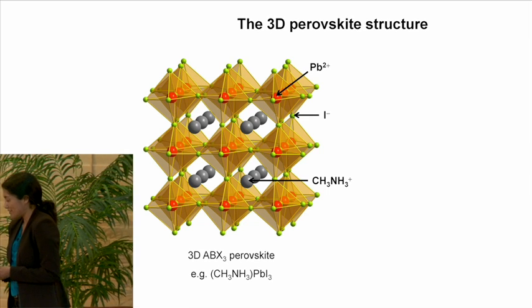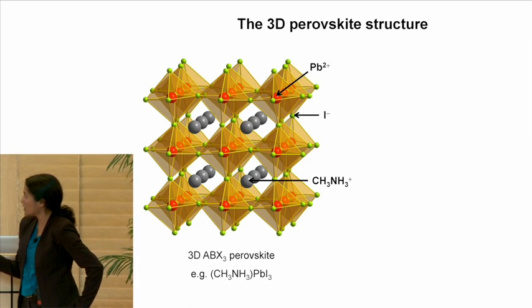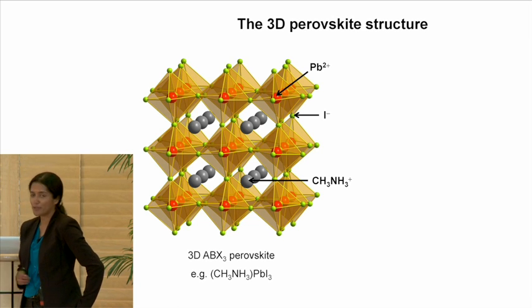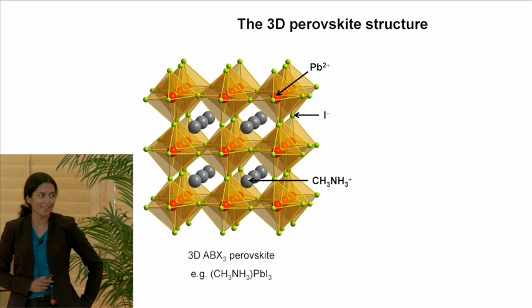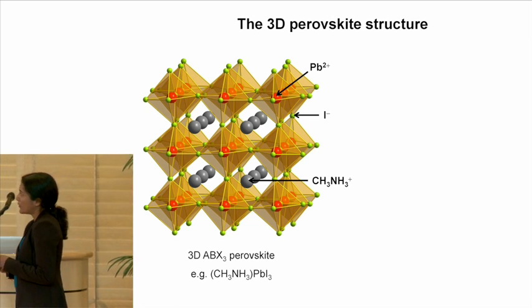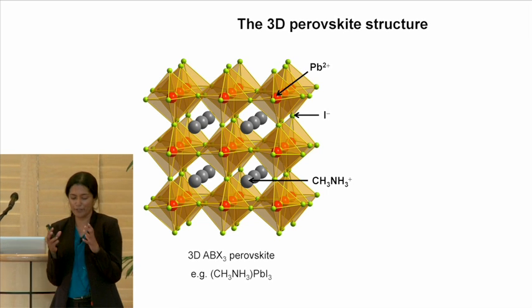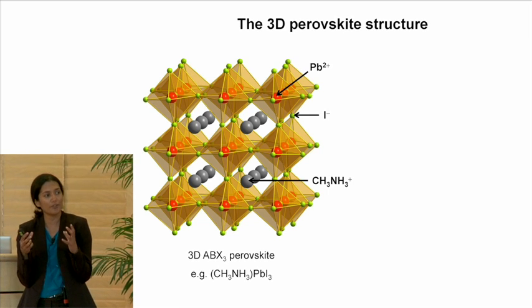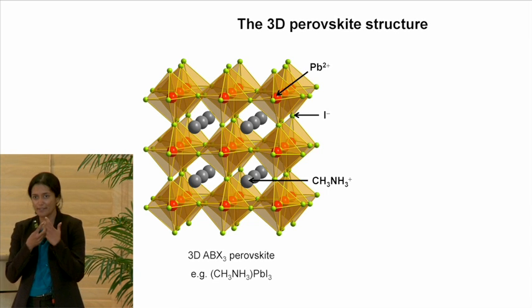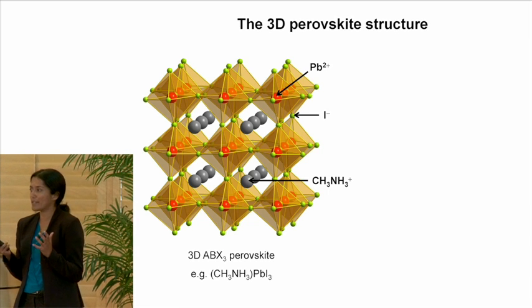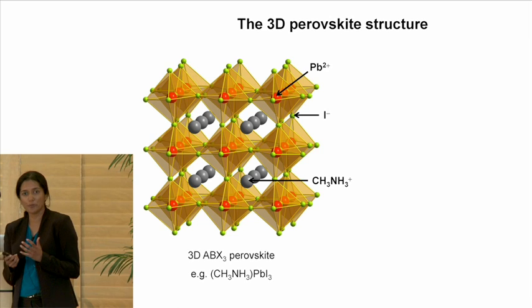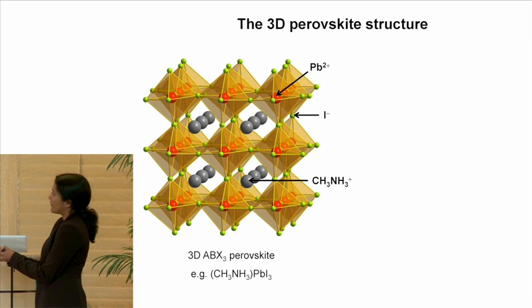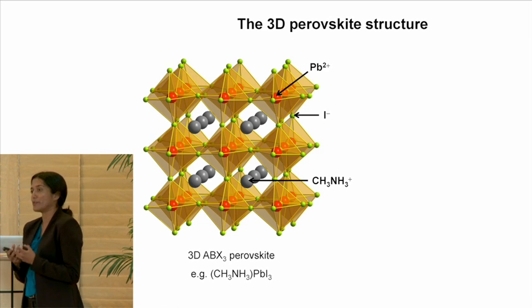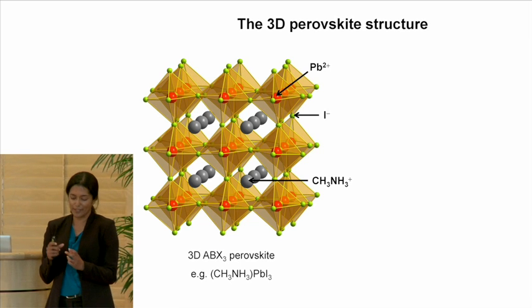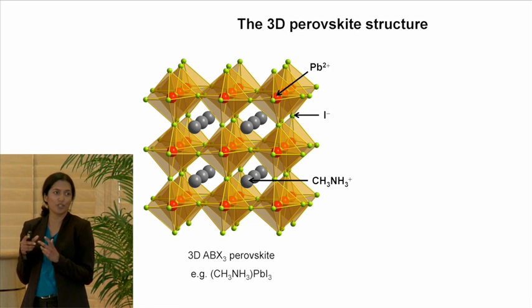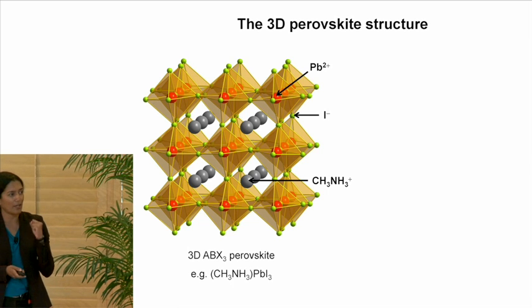These materials have the same general overall structure. Here I show you the structure of this lead halide perovskite material that has caused so much excitement in the photovoltaics community, where the inorganic framework just consists of a very simple framework of lead halide octahedra that share corners. This extends out in all three dimensions, and this framework has a net negative charge. So therefore, to provide charge balance, we need very small positive ions that have to reside within the cavities of this structure. Within each cavity that's defined by 8 corner-sharing octahedra sits a very small organic cation.